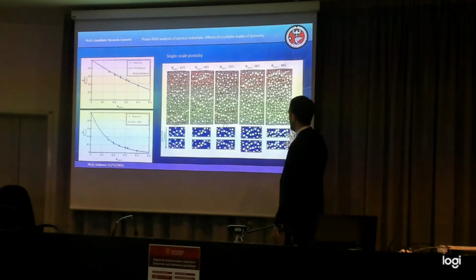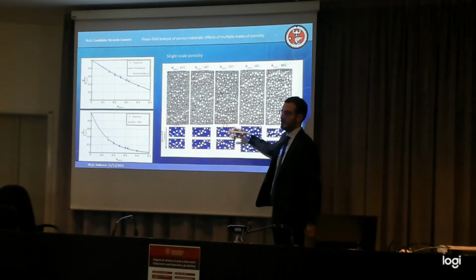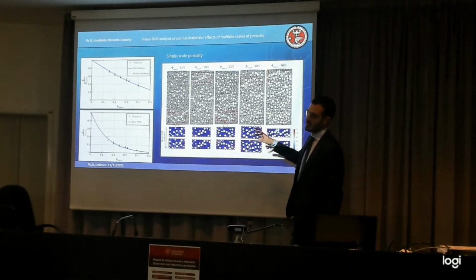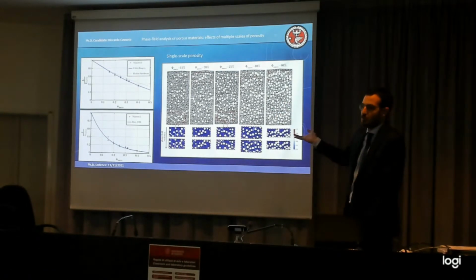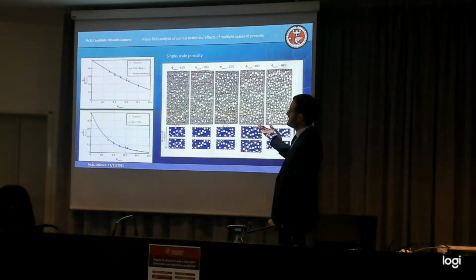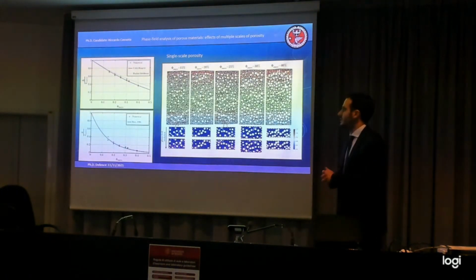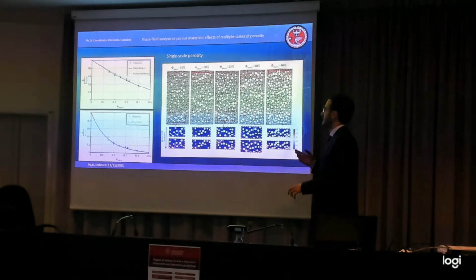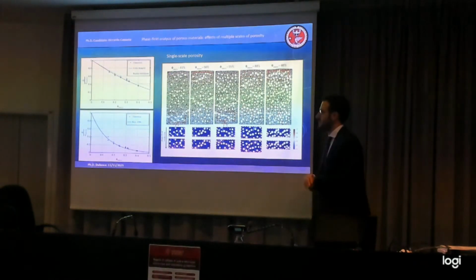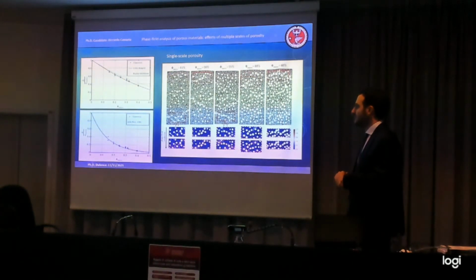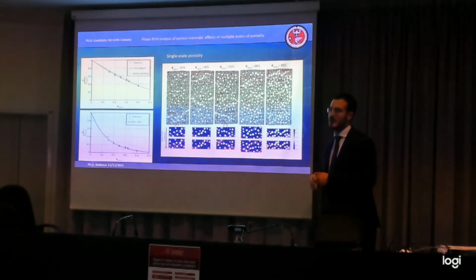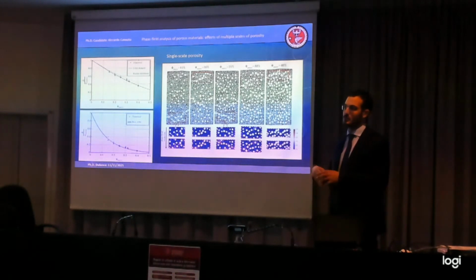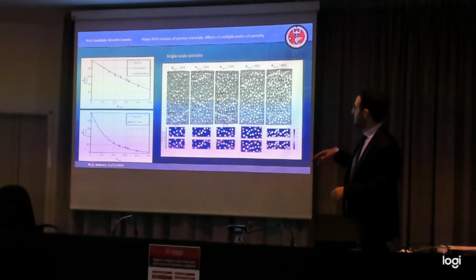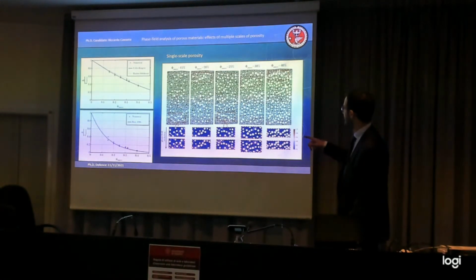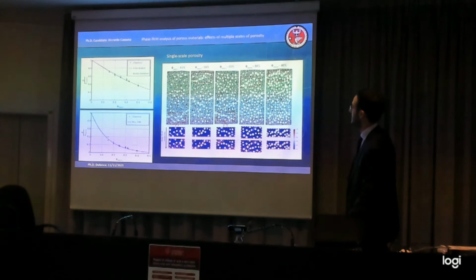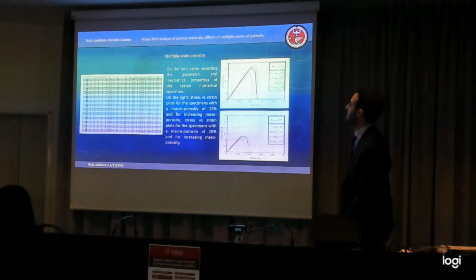But in terms of the phase field, I mean the crack pattern, that is not the case. There is no fast analytical solution, obviously. There is the MSA method, which is a geometrical one. It relies on a minimal solid area, but it does fairly badly also when you try to predict where the crack is going to develop. So the onset is a problem too. And so the phase field is perfectly capable of developing spontaneous cracks.